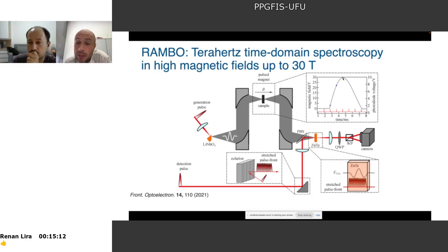For example, this is a magnetic field pulse of 30 Tesla. So this light pulse will measure something like 3 Tesla. This one here will measure something like 23 Tesla. And this one here will measure 30 Tesla. So this is a technique that depends on single shot detection, only one shot of light for different magnetic fields. The detection is made with a camera, so we collect all the time points at the same instant, instead of collecting point by point the waveform of the electric field.